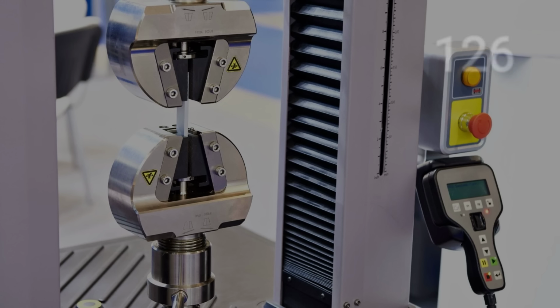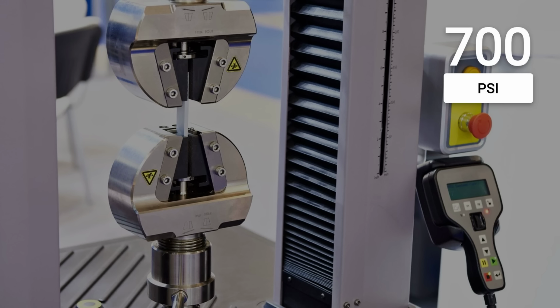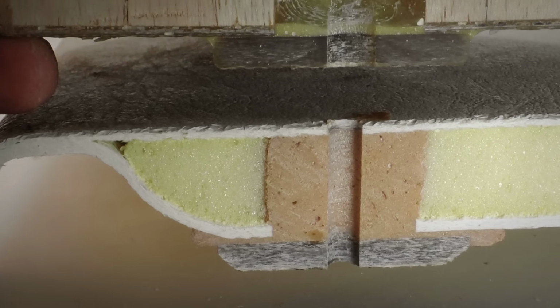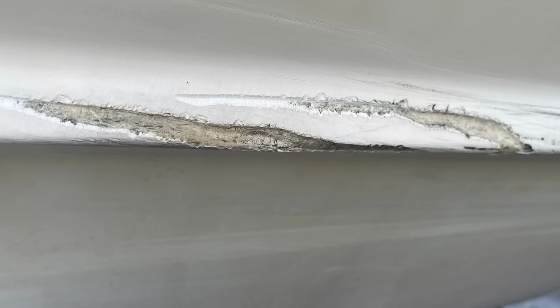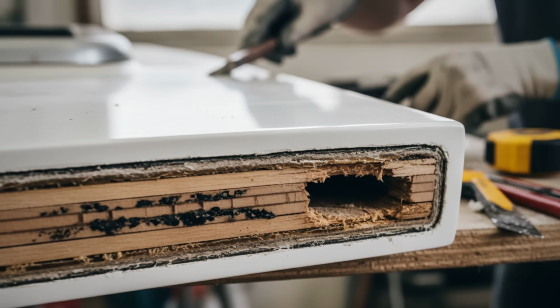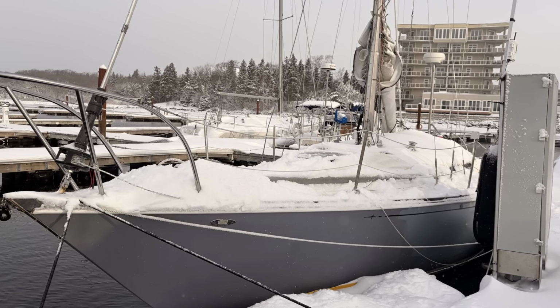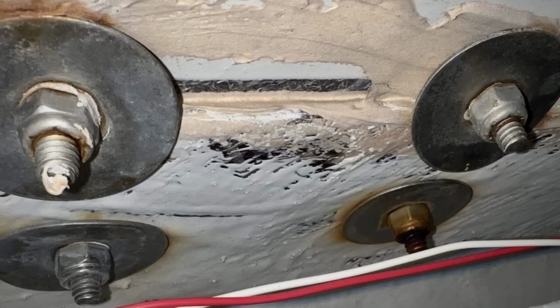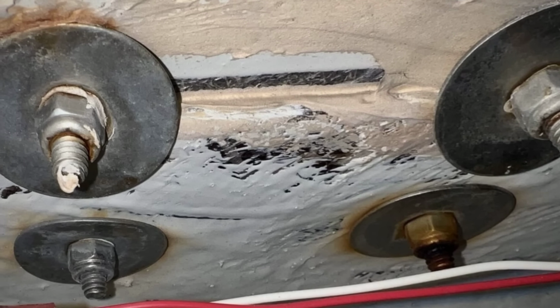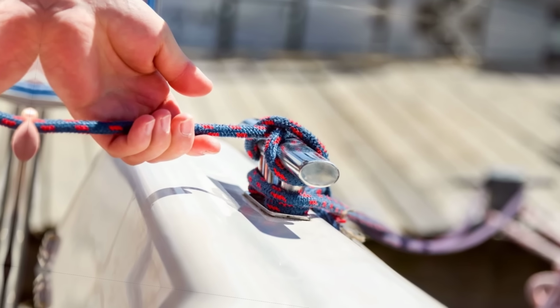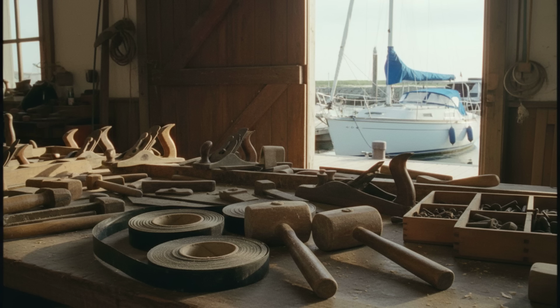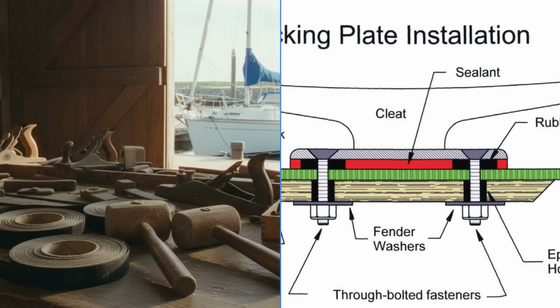3M 5200 sets up with a tensile strength of about 700 pounds per square inch. That is not just sealing a fitting, it is welding the hardware to the thin top skin of a cored fiberglass deck. The balsa core underneath has no say in the matter. Fast forward a few seasons. The stainless bolts holding that cleat start to work back and forth, just a hair, with every wave and every dock line. Polyurethane does not forgive. Unlike a gasket, it does not compress and relax. It stretches, then snaps back, transferring every bit of movement straight to the gel coat.